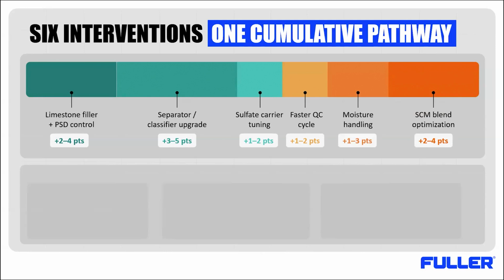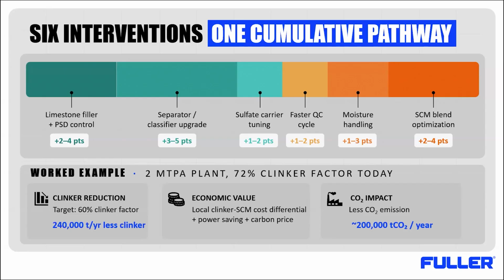The point here is not to add these numbers blindly. The real value depends on the plant constraints, material quality, and market requirements. So in the working example here, moving a 2 million tons per annum plant from 72% clinker factor to 60% means about 240,000 tons per year less clinker and roughly 200,000 tons of CO2 avoided per year. The key message here is that the existing asset should be audited before a major capex is justified.